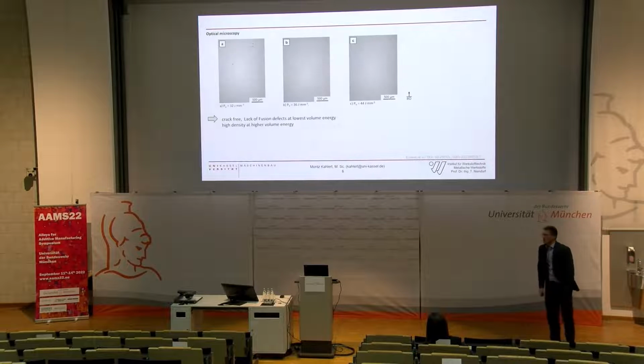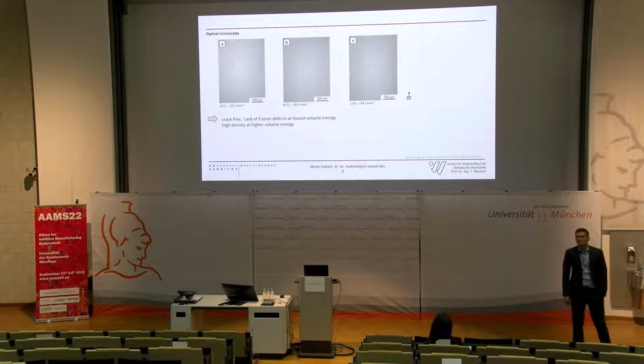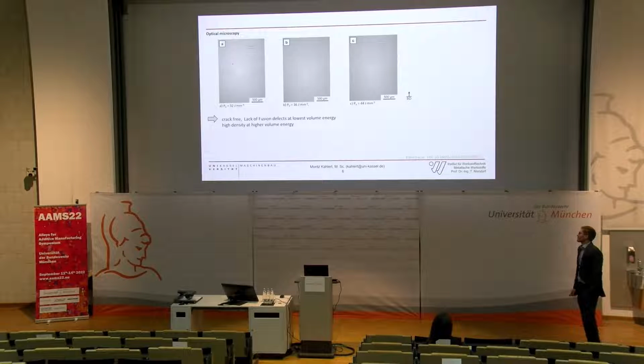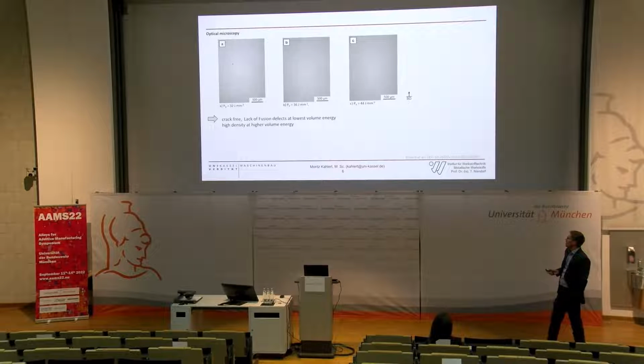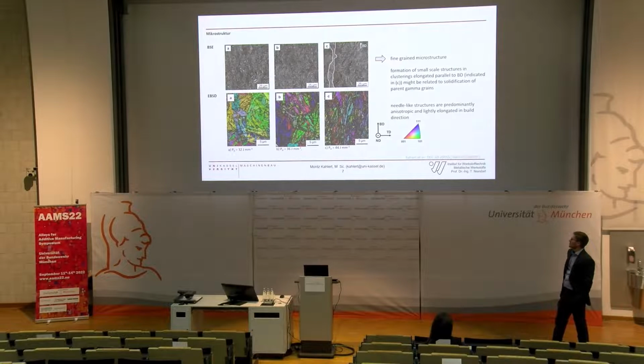When we look at the optical microscopy of the specimens produced with these 3 volume energies, we can see 3 crack-free specimens, but with lack of fusion at the lowest volume energy. At the higher volume energies, there are no cracks and no lack of fusion in the specimens.